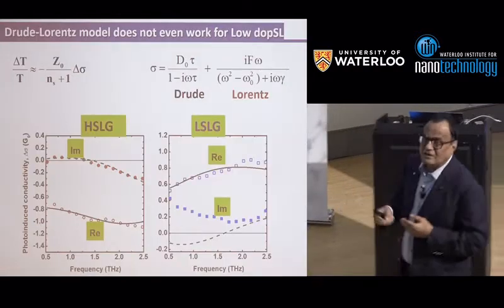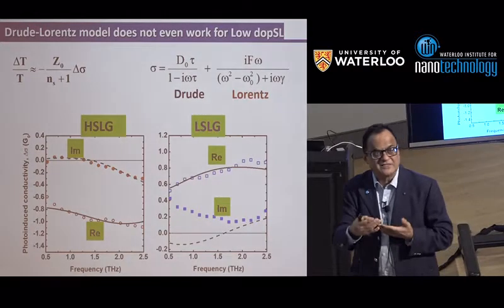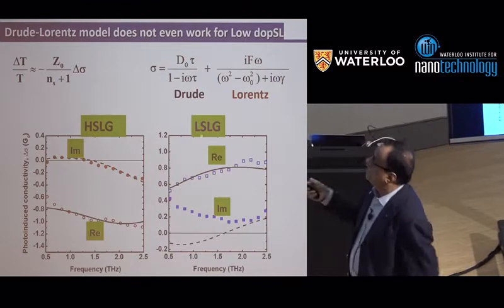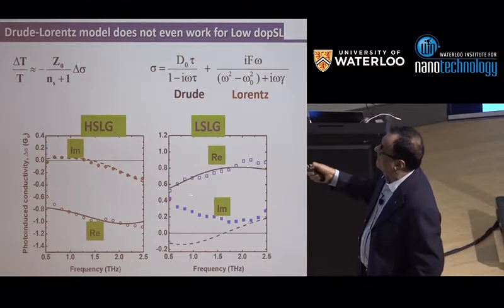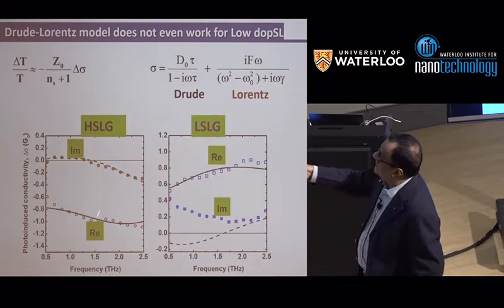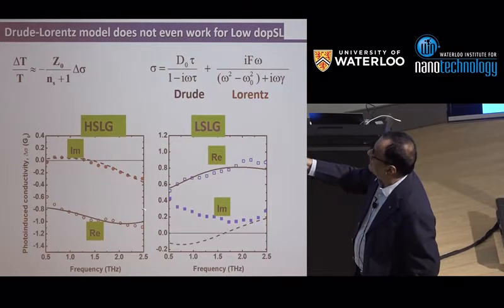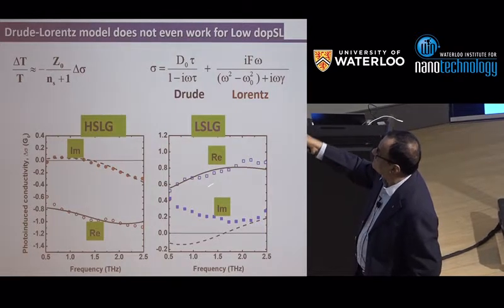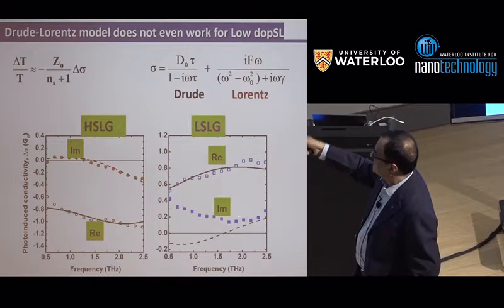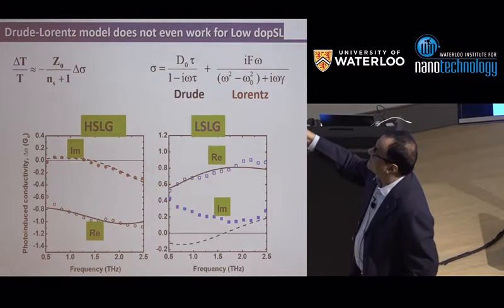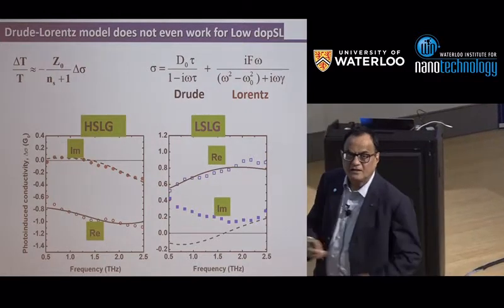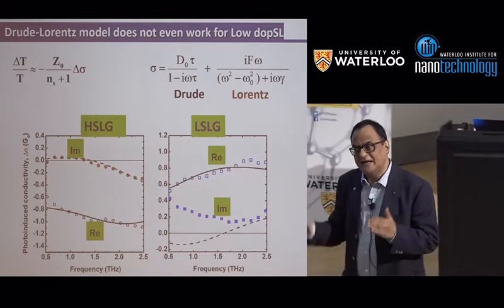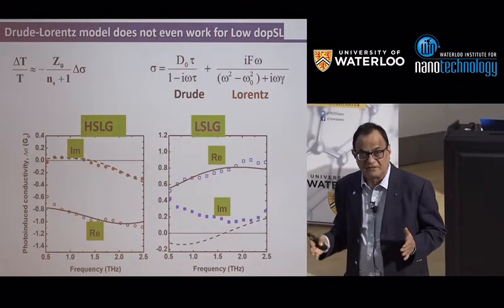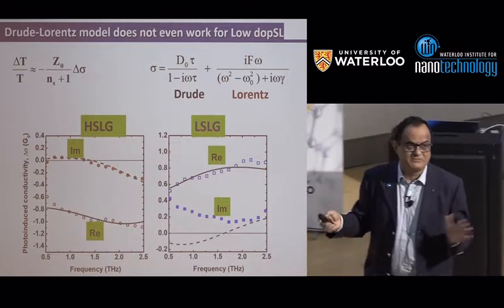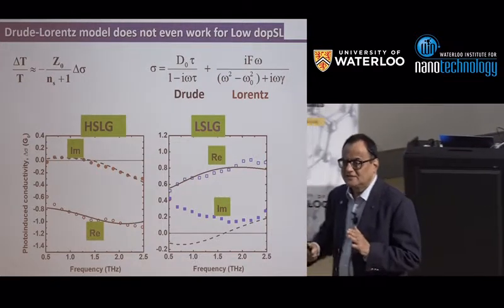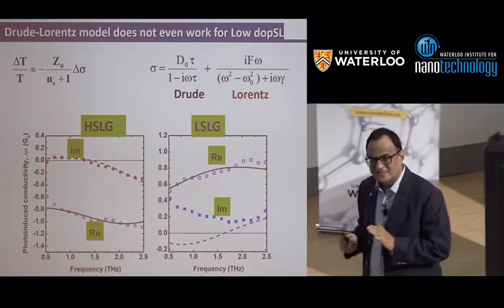And then we were stuck when we changed our graphene samples, many of them, and when we went to low doped graphene, this is the data which is very different from high doped graphene. Imaginary part is positive, real part is positive with this kind of a shape, and nothing works. We put Drude, we put Lorentzian, nothing works. So even this ad hoc assumption is not sufficient. So then, and this is where we decided that this is not good for us to do.